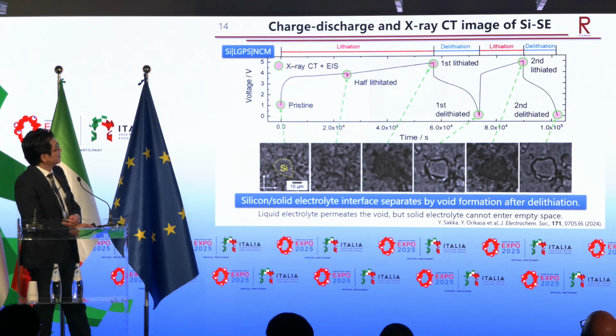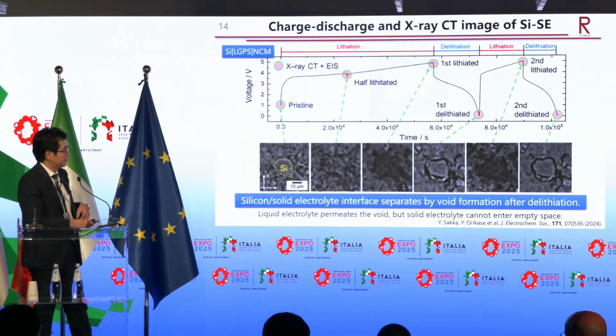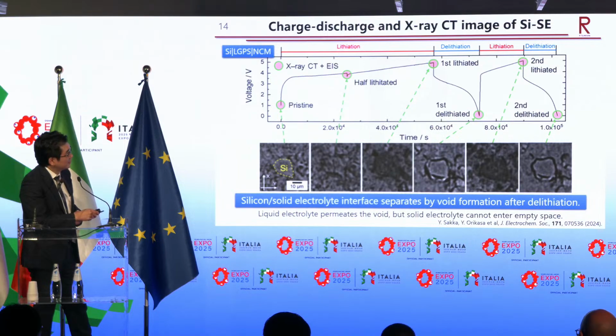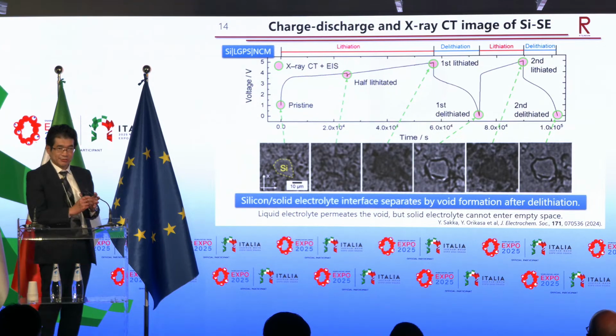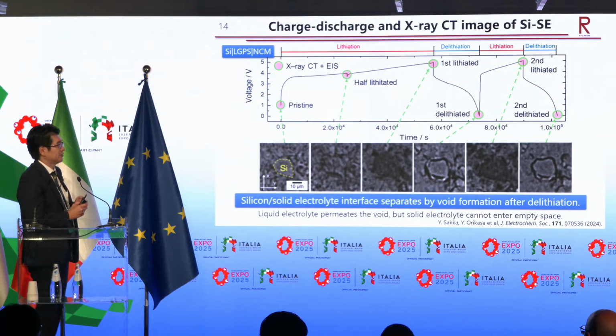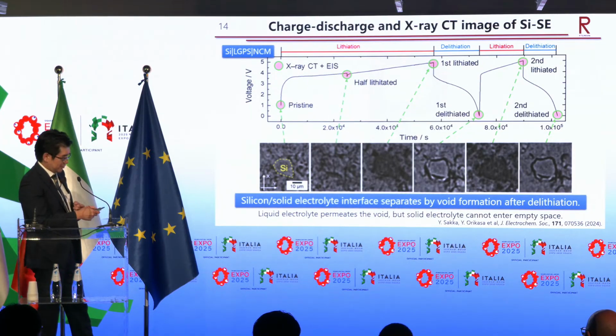So this figure shows the charge discharge profile. And also, we measure the X-ray CT using the same cell. And this is a silicon active material. During charge, silicon is expanded due to the lithiation of silicon active material here. And then for the discharge reaction, silicon shrinks due to the extraction of lithium ion. And also, for the subsequent charge discharge, silicon is expanding and shrinking.